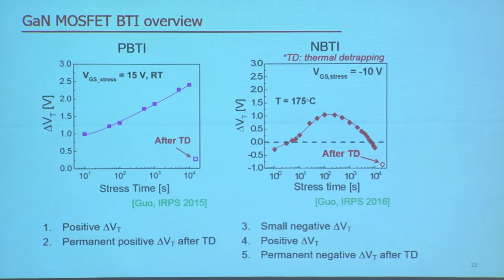Next, we look at the NBTI side of the picture, and there are three regimes here. Here we stress the device at negative 10 volts at 175 degrees C, and we see regime 3, which is a small negative VT shift at low stress time, and it becomes positive, and this is regime 4, where you see this positive VT shift. And then as we continue to increase stress time, we see a leftover or a permanent negative delta VT after thermal detrapping. So next, I will report the 5 different regimes separately.